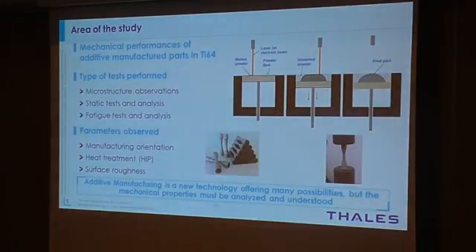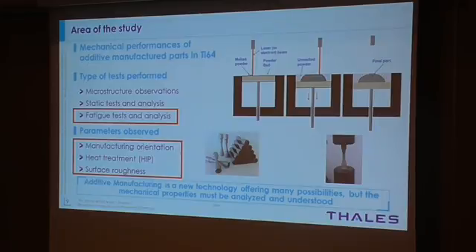And in order to ensure their mechanical properties, I am studying the mechanical performances of additive manufactured parts produced in titanium 6-4. So I study microstructure, static test, and analysis, and I study 3 parameters: the manufacturing orientation, the heat treatment, and the surface smoothness. I use the same technology as Matteo, but I call it differently, SLM instead of SLS, for selective laser melting. In this presentation, I will focus on fatigue tests and on the 3 parameters that I mentioned.